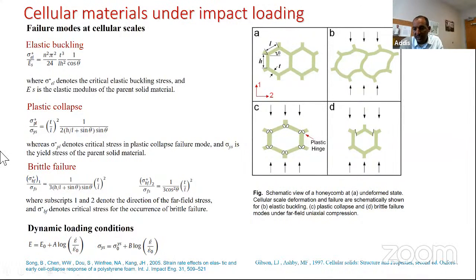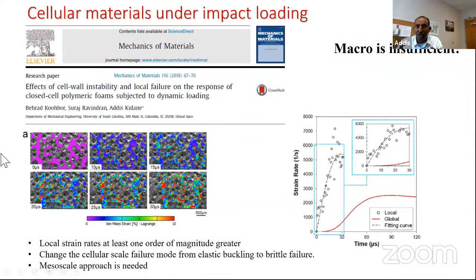What we found in our study, with this digital image correlation experiment at small scale, is that the local strain rate in this material is not the same as we think in the continuum scale material response. For example, in this curve, this is the global strain rate response. If you average the whole specimen, this is the strain rate you get, around 2000 under these impact loadings. But if you focus on a local region and measure the strain rate there, it could be as high as one order of magnitude compared to the global.